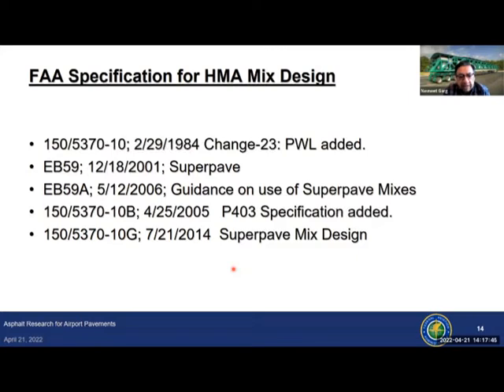5370-10G that was released in 2014 added superpave mix design, because till 2014, all HMA mix design was done using the Marshall mix design procedure. And we added superpave mix design, not because we had any problems with Marshall mix designs. These mixes were performing well on airports. It's just that it was getting difficult to find labs that have Marshall mix design equipment.